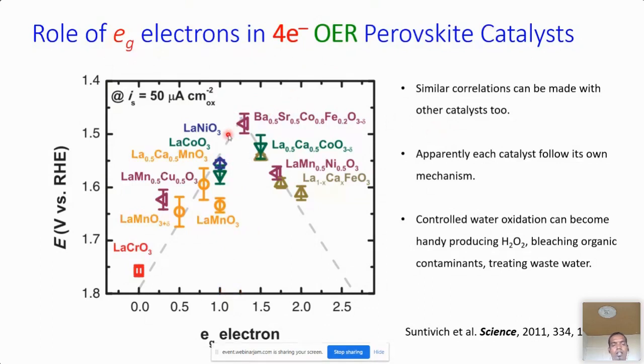So in the case of ORR, we saw that EG electron occupancy from 0.5 to 1 was the best, and in the case of OER, the catalysts with EG electron occupancy from 1 to 1.5 are the best. With this in mind, one can even design or generate a catalyst which can perform both OER and ORR as a bifunctional catalyst.